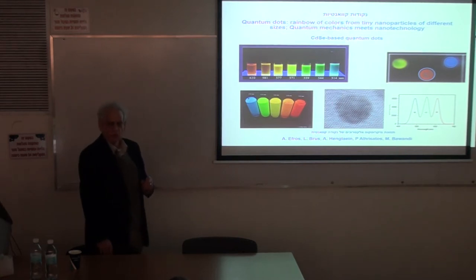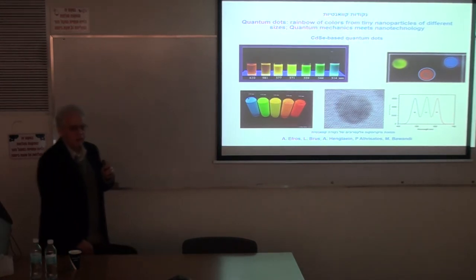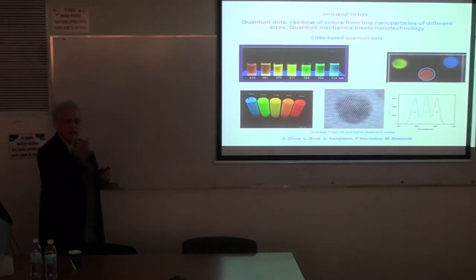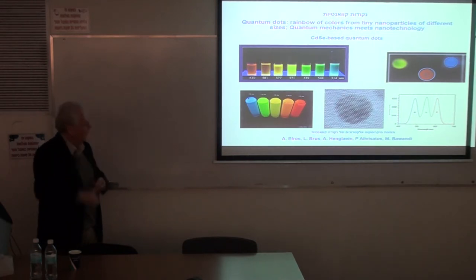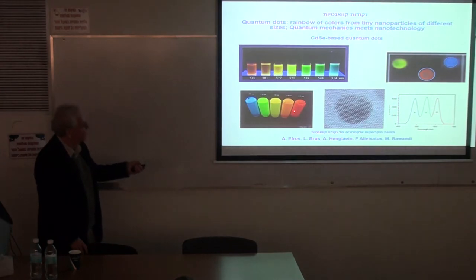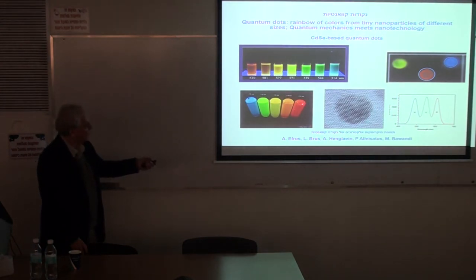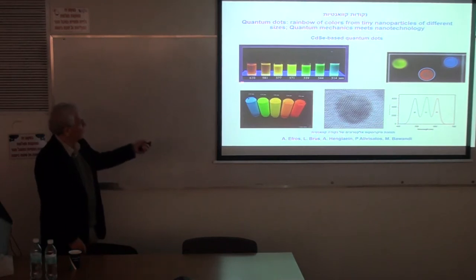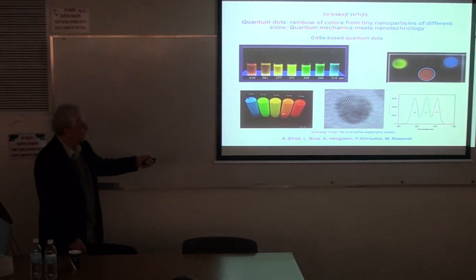Let me go now to perhaps the most important part of my talk, or one of the highlights, which is quantum dots. Quantum dots are the most beautiful example demonstrating the Schrödinger equation, the quantum size effect. So basically, it tells you that if the electron is confined to a smaller and smaller nanoparticle, the difference between the energy bands will grow, and consequently, the material will start to absorb more toward the UV, across the entire visible spectrum. So you see different cadmium selenide based quantum dots, and this one is the largest one, and this one is the smallest one, and this beautifully demonstrates the absorption and luminescence of these nanoparticles.